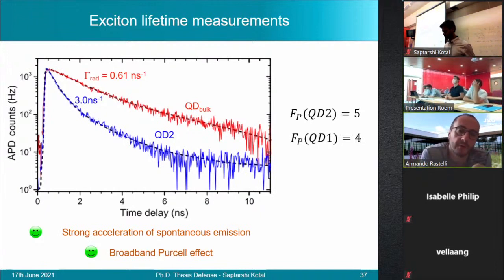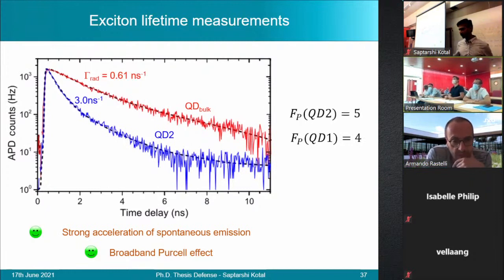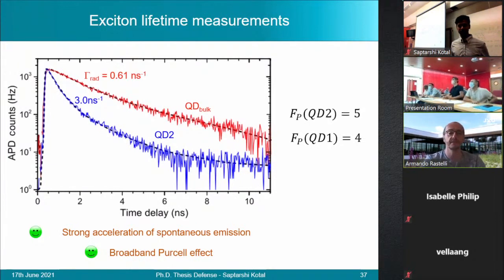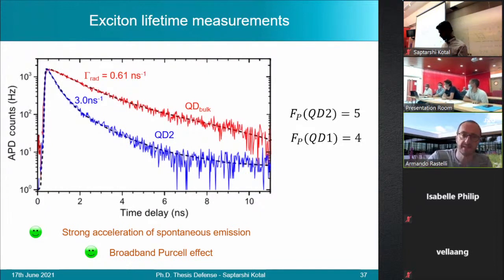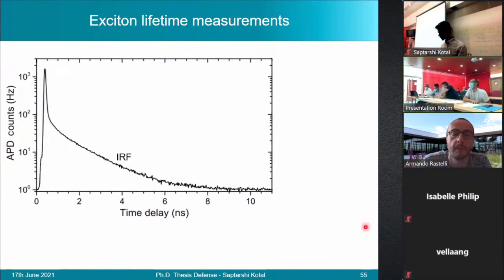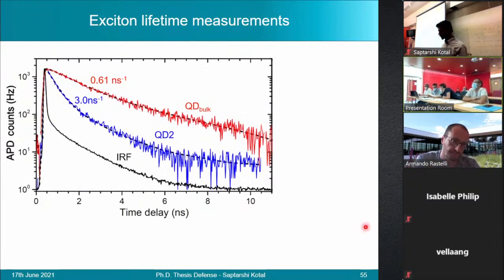So for the QD bulk, you say this is a neutral exciton, and probably this biexponential decay comes from dark exciton, bright exciton flip. But then, why do you see that also for QD2? We don't see it for QD2. What you're seeing here, which looks like it might be a biexponential decay, is because it's convolved with the response of the setup. I see. So this kind of bend you attribute to the response function. This is what the response function looks like. And then we convolve this with an exponential to get this fit.